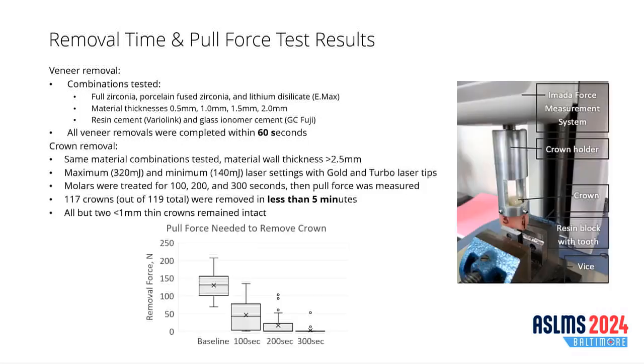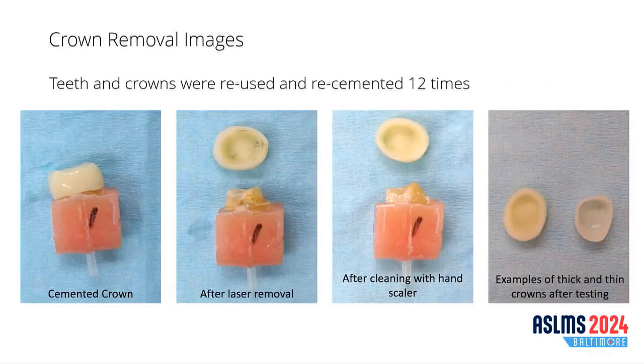For crown removals, we tested pull force necessary at 100 seconds, 200 seconds, and 300 seconds. All crowns except for 2 were removed in less than 5 minutes, and for the 2 that remained still adhered to the molar, you can see the pull force was greatly reduced. You could remove them by hand. And all but 2 very thin crowns remained intact.